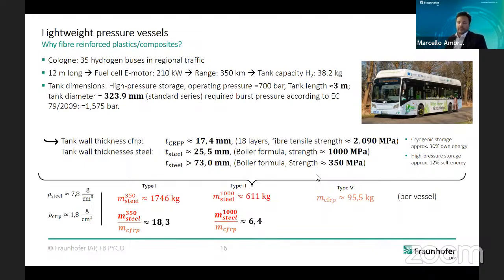So why fiber reinforced plastics or composites? In this case, we have a hydrogen bus in the region of Cologne with a tank which has an operating pressure of 700 bars and a length of 3 meters with a diameter of around 0.3 meters. And when we design it, for example for type 1, it would have a mass of 1.7 tons. And as we add some carbon fiber to type 2, as I showed you before, we already decrease to 611 kilograms based on the fibers that we will use.